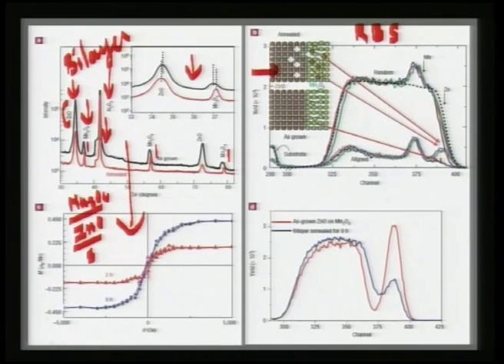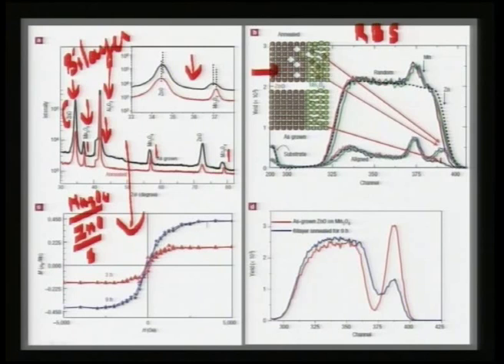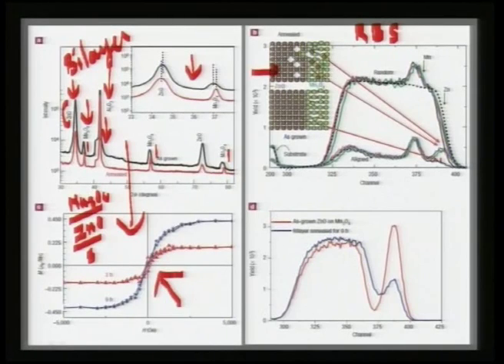If you take such a film and heat it — representing the configuration of sapphire / ZnO / Mn3O4 — and take a VSM loop, you see that with more and more annealing temperature the ferromagnetic loop is developing. This could actually happen at the interface because of inter-diffusion across the layers rather than substitution. More and more zinc is getting incorporated into the Mn3O4 lattice and as a result the magnetic moment is picking up — incidentally this signature is comparable to what is reported.